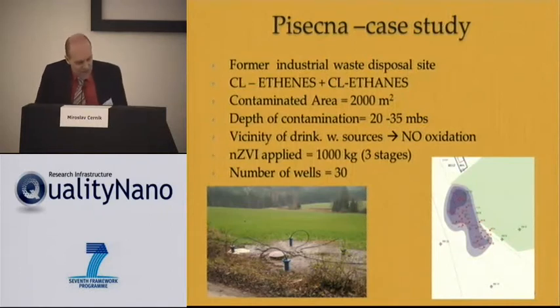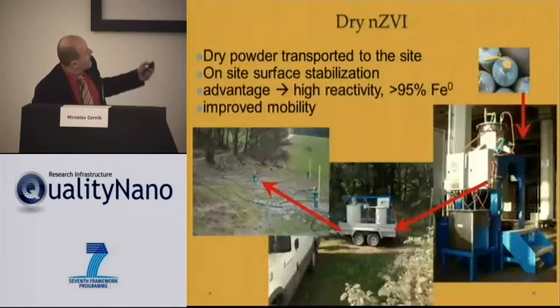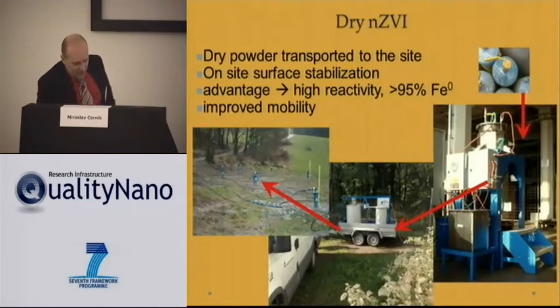This is the site called Písečná in the Czech Republic, which is a former industrial waste disposal site, contaminated by chlorinated ethenes and ethanes. The area of contamination is not so large, about 2,000 square meters, but the contamination is at a depth below 20 meters, and in the vicinity is a source of drinking water, so there is no possibility to use some aggressive method like chemical oxidation, for example. We applied nanoparticles in an amount of about 1 ton in 3 stages to 30 wells, and I will show you the results.